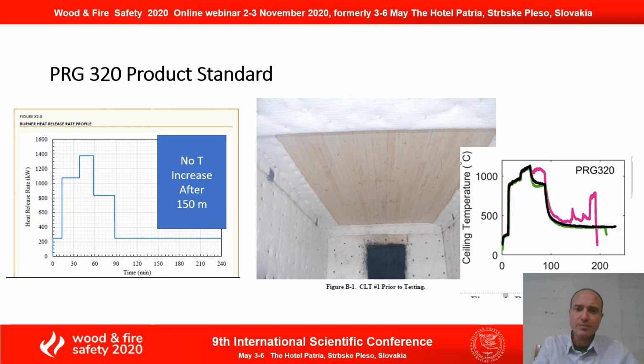Finally, I wanted to talk a little bit about this PRG 320 product standard. So to qualify yourself as a CLT adhesive in the United States, you need to pass a full-scale test where it's very similar to the FPRF test, where it has a similar opening factor, and you need to be exposed to a similar temperature profile as the FPRF test and not have any temperature increase at the end of the test. And so in this little figure here, there's 3 different adhesives that were tested.